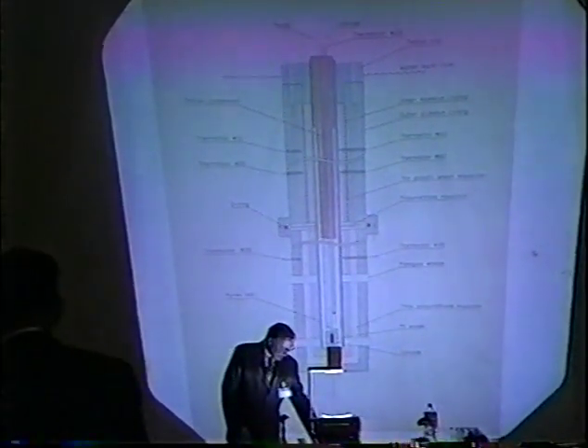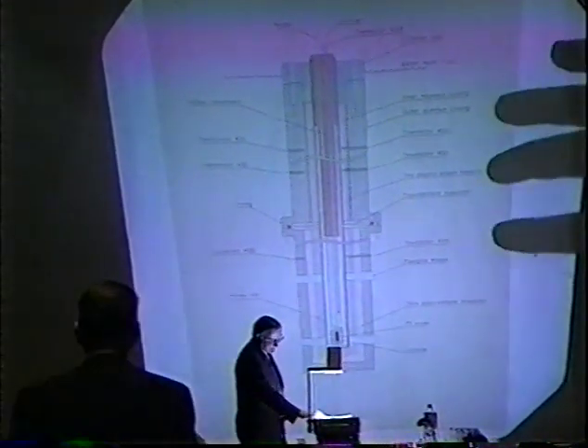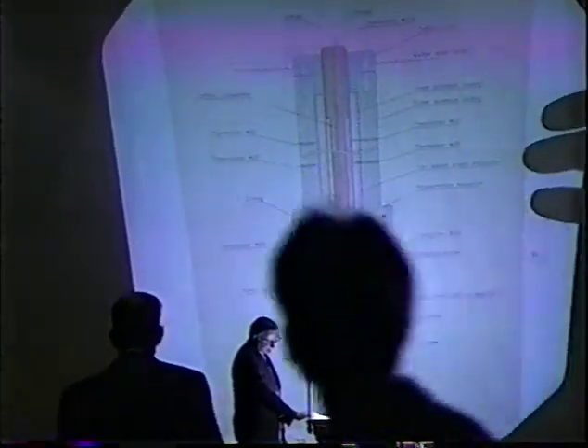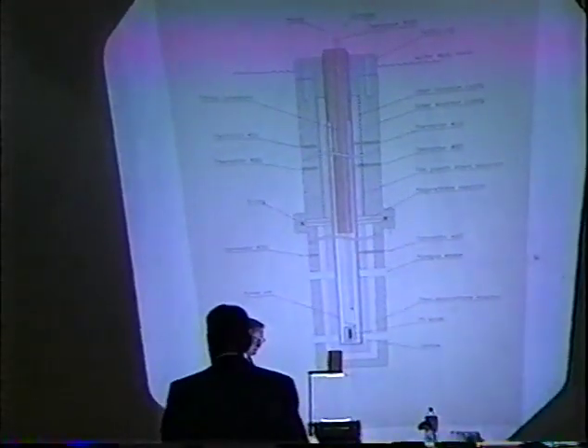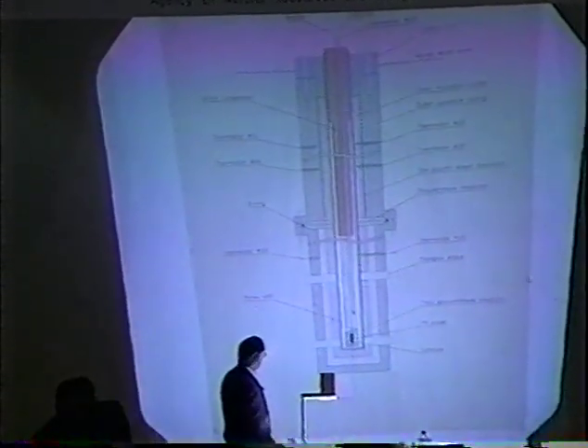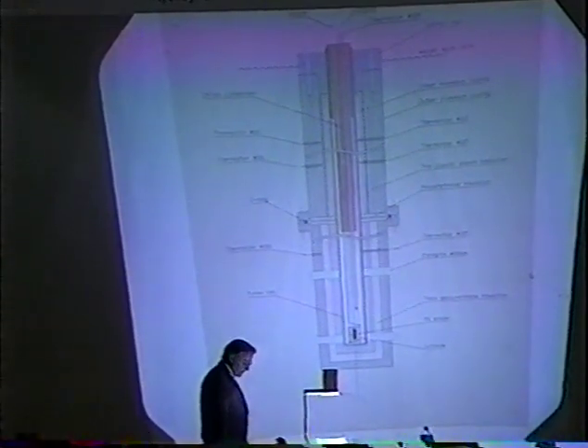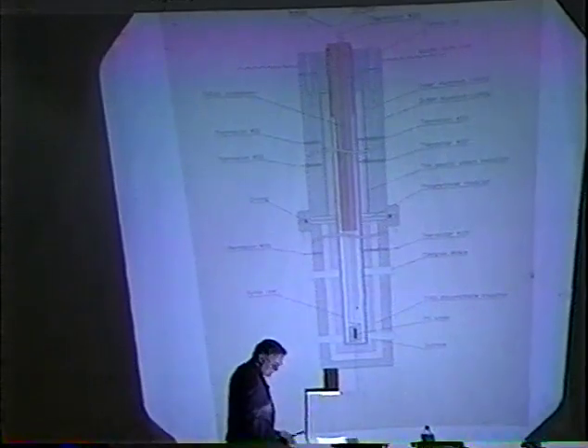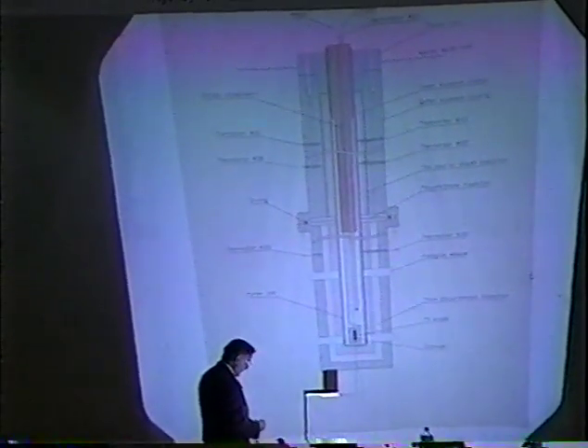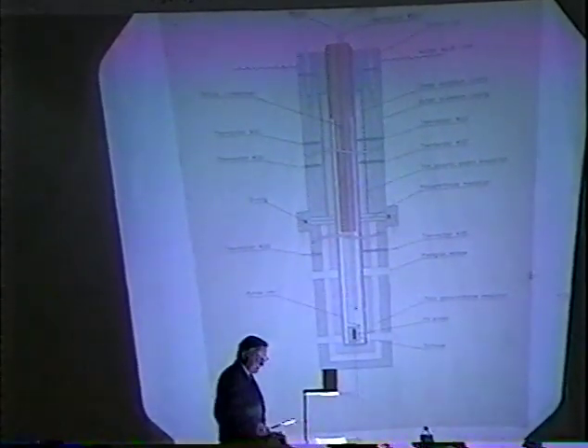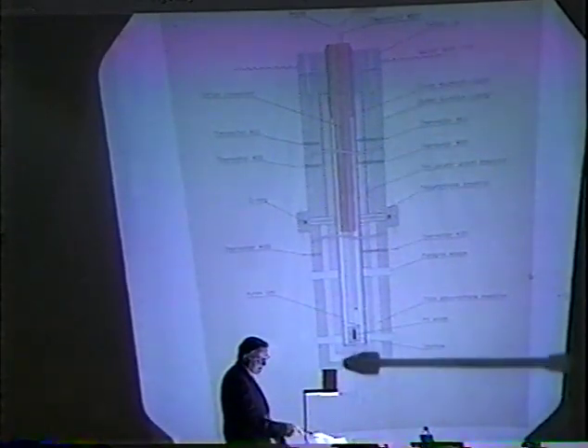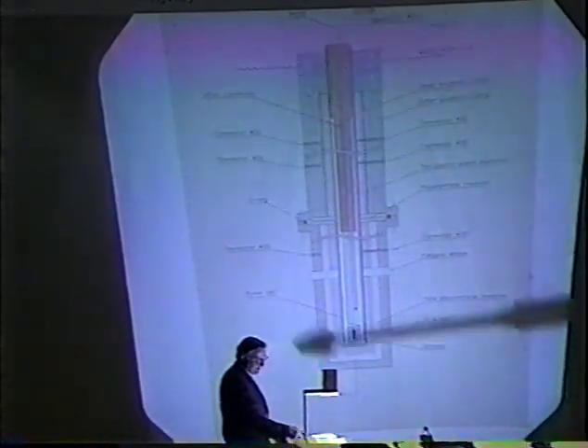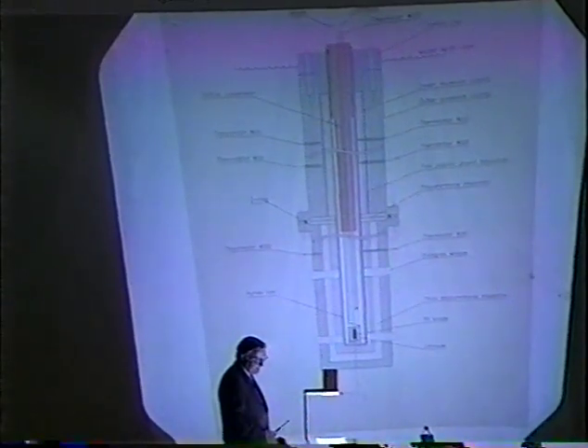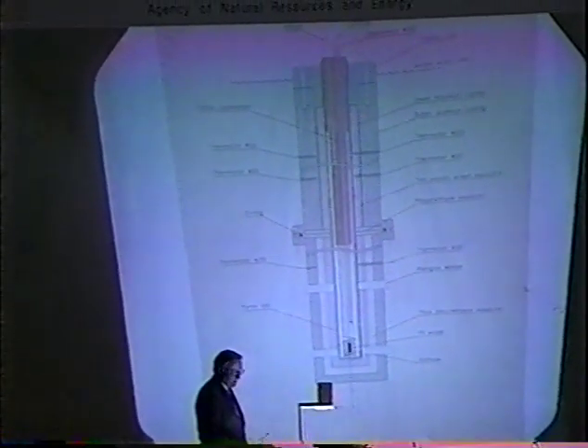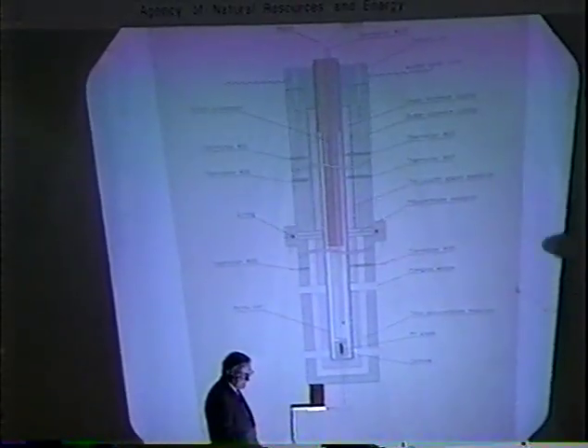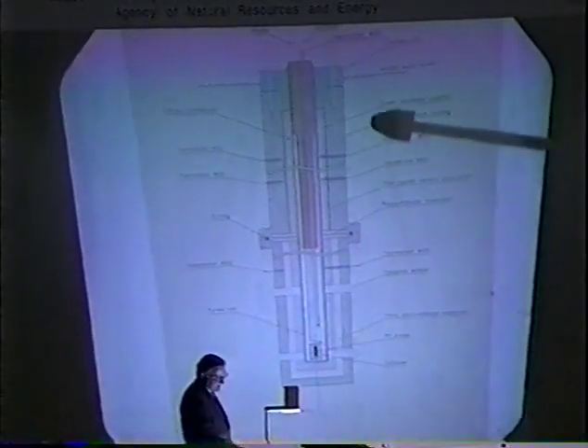So about that time, Professor Fleischmann, for those reasons, designed a calorimeter very similar to this schematic, which is shown here. This calorimeter is a double linear heat flow calorimeter. It is composed of a metallic outer casing. The entire calorimeter is submerged in a thermostatic bath, which is held to within 1 or 2 hundredths of a degree centigrade. The principle of operation is quite simple.